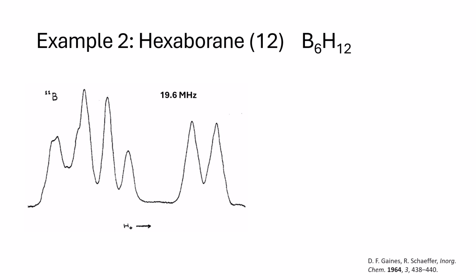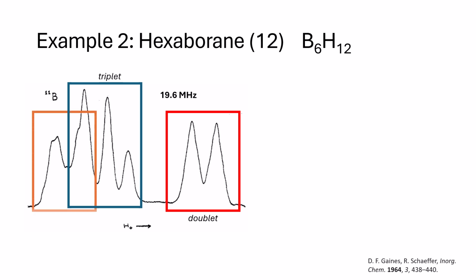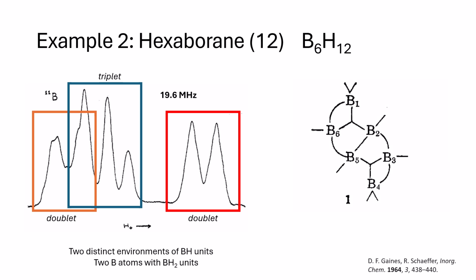A different example of boron structure determination with NMR is hexaborane(12). In its NMR spectrum, shown here, we can see that there are 3 distinct chemical environments: a doublet, a triplet, and another doublet that overlaps with a triplet. This indicates that hexaborane(12) has 2 distinct boron chemical environments with BH units, as well as 2 boron atoms with BH2 units. And hence this supports Lipscomb's hypothesis for the structure of this compound, which looks like this. In the structure, B1 and B4 are the BH2 units, while the other 4 boron atoms form the 2 distinct BH units.